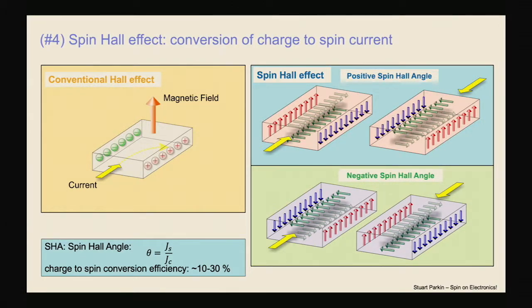But again, in the last 3 or 4 years, there have been some very interesting developments, and even simple metals like platinum and certain forms of tantalum and tungsten generate efficiencies, once you take account of the transparency of the spin current at a magnetic, non-magnetic interface, of the order of 10 to 30%. So these charge to spin current efficiencies are much larger than was anticipated just a few years ago.